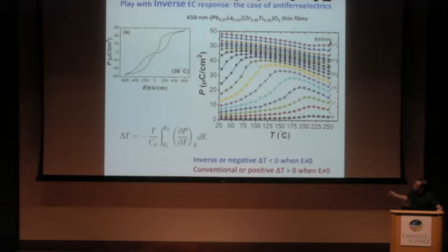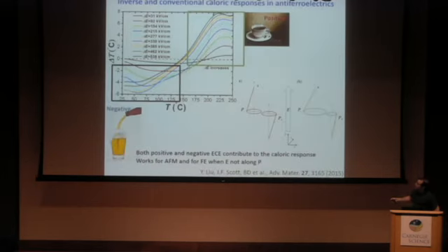And if we now plot the polarization as a function of temperature for different electric fields, let's start with the high electric field. You see that the polarization is decreasing while the temperature is increasing. Of course, if you inject the derivative here, you will have delta T positive. However, when the electric field is lower, you start by having an increase of the polarization first. If you have the increase of the polarization, this derivative now is positive, and then as we have a minus here, delta T becomes negative. And indeed, in case of this antiferroelectric, we have a negative or inverse electrocaloric effect and a positive or conventional electrocaloric effect.